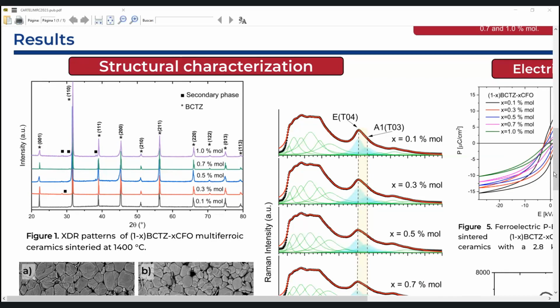Regarding the Raman spectroscopy results, the spectrum was deconvoluted and a fitted curve was obtained. A characteristic pattern of a mostly rhombohedral perovskite is observed. A Raman shift was noted at lower wave numbers for the E(TO4) vibration mode. This mode corresponds to the stretching of the bond of the titanium and the zirconium cations with the oxygens to which they are coordinated. The Raman results indicate that there are bond elongations that are favored with the increase of dopant in the ceramics.